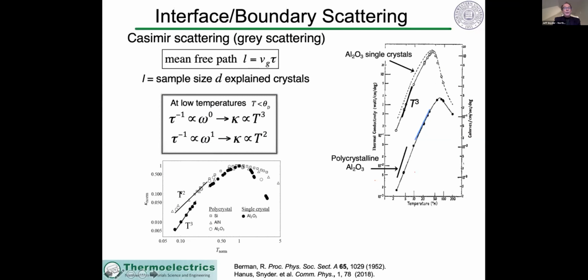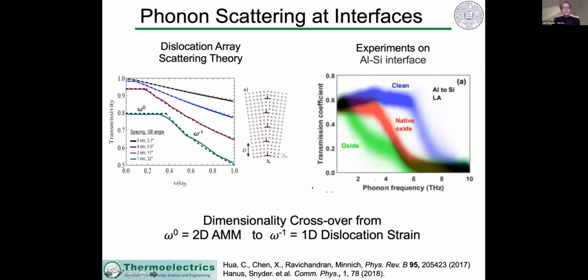But for polycrystalline materials, we've been using the same type of boundary scattering model for decades, even though if you look carefully at polycrystalline materials, the temperature dependence behaves more like T squared. And so we think this has something to do with a different mechanism for interfaces and boundaries than the simple Casimir limit that we've used frequently in the past.